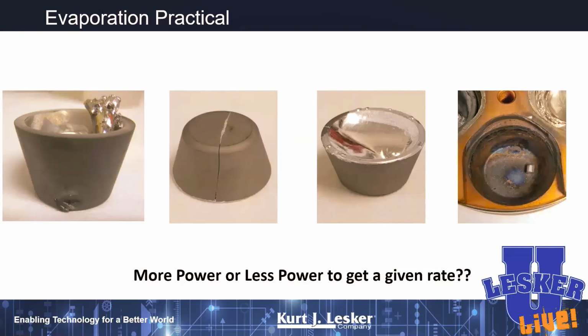Other things that go weird on these crucibles: if you're doing things like silicon, silicon tends to grow up out of the crucible in the direction of the beam. I can't tell you right now why it does that, but it does. Very, very crazy. If you do have a material which has gotten molten in your crucible, after a few cycles, it will crack the crucible. And once it cracks the crucible, you'll notice you'll need more and more power to do your deposition, because some of your metal in the crucible is actually in direct contact with the water cooling jacket.